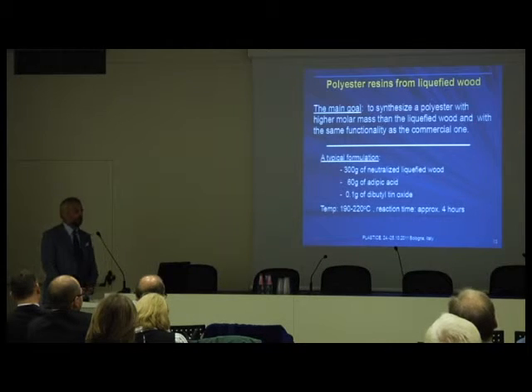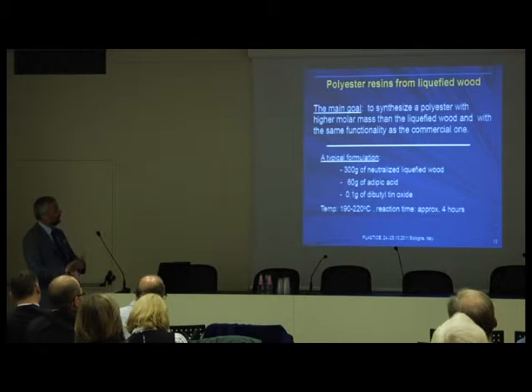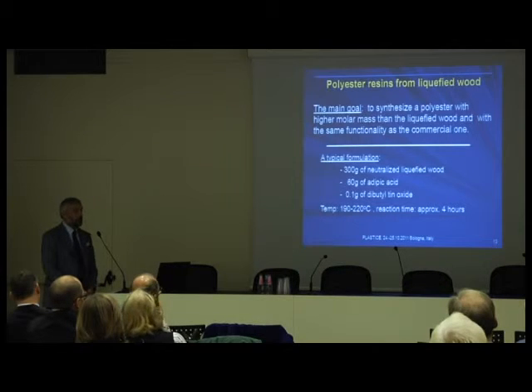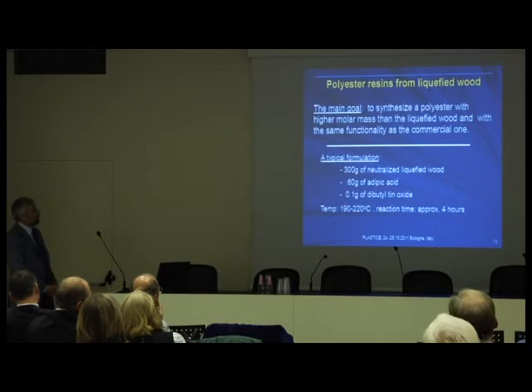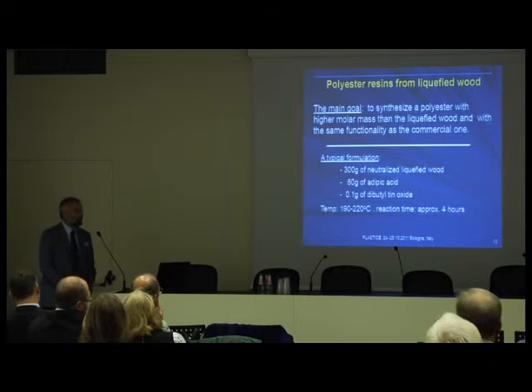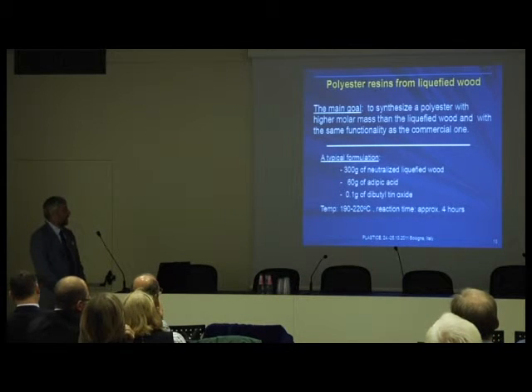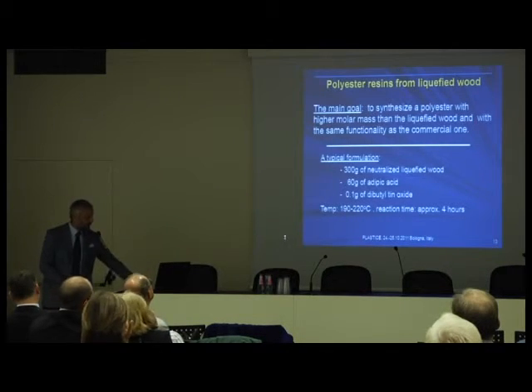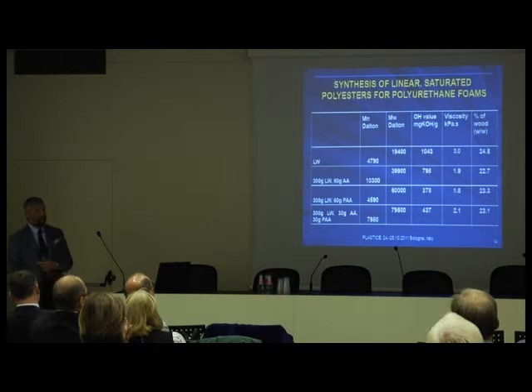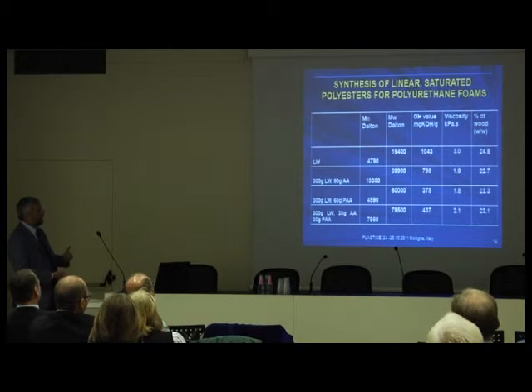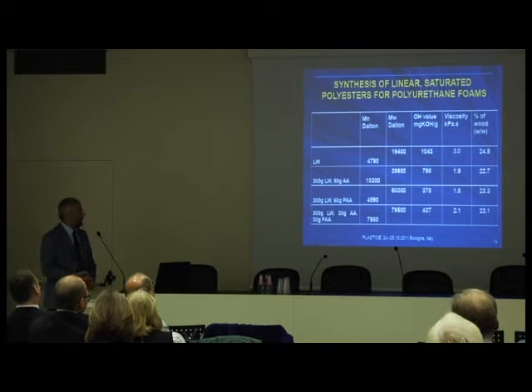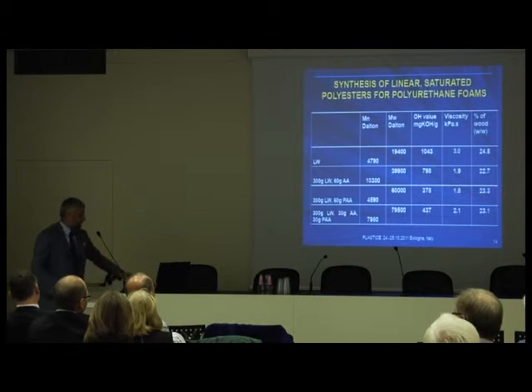As I said, the liquefied wood has a lot of OH groups, so why should we not use this material as a polyol in a polyester synthesis? As you can see from this typical formulation, we use liquefied wood, some adipic acid or phthalic anhydride, and of course we need some catalysts for the transesterification process. At the end you get a very nice product with higher viscosity, higher molar mass, and on the other hand lower OH value, which is also quite desirable in the reaction with isocyanate.